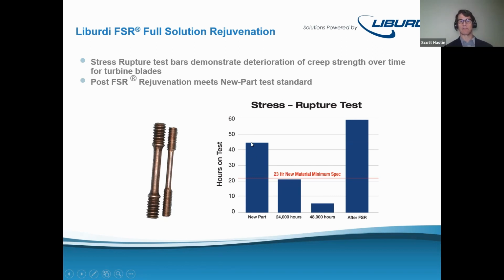So what we'll see after 24,000 hours of service, you're going to see some of that agglomeration of the gamma prime structure, and you'll start to see the time to stress rupture drop on that material. Not a big deal, can continue running in service, and that's expected. But after 48,000 hours, you're going to see a significant drop from the new material minimum.